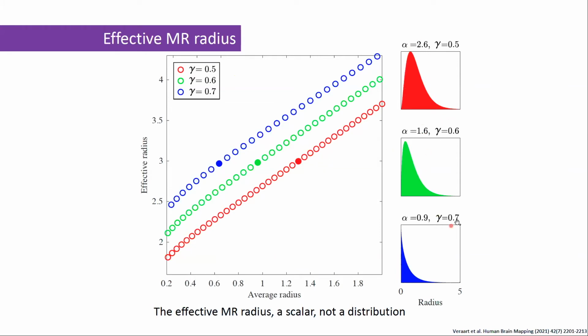I generated 3 distributions. They're all gamma distributions with different shape parameters. What's interesting about those 3 distributions, which are clearly different, is that the average radius varies strongly from about 0.6 to more than 1.2. However, if we compute the effective radius by dividing the sixth order moment by the second order moment, we can see that we end up at the same value. So we cannot go back from the effective radius to the average radius without knowing the exact shape of our axon diameter distributions, which is unfortunately not known.